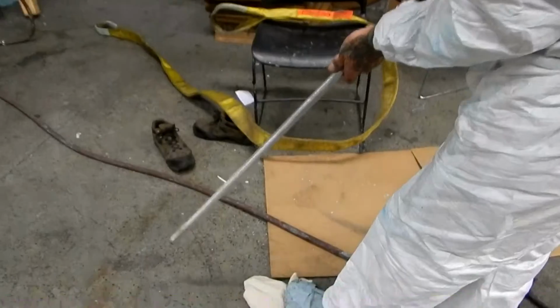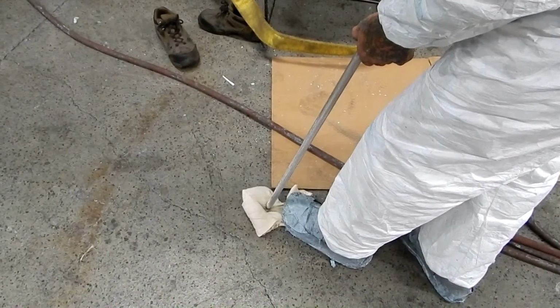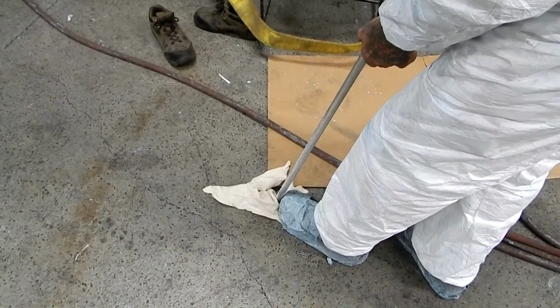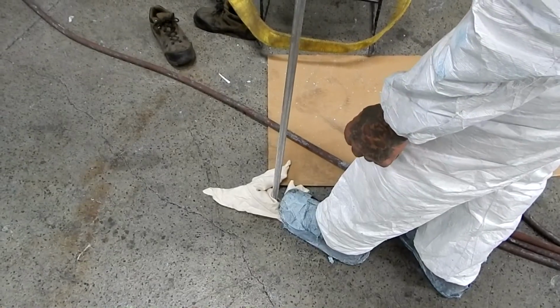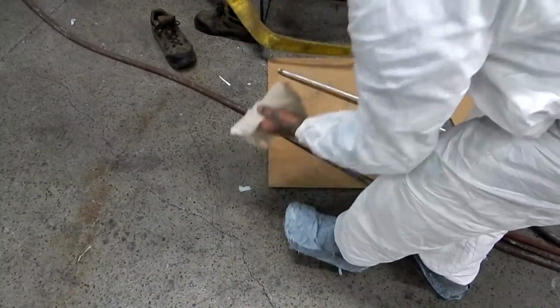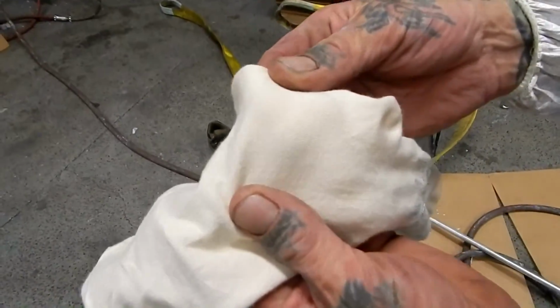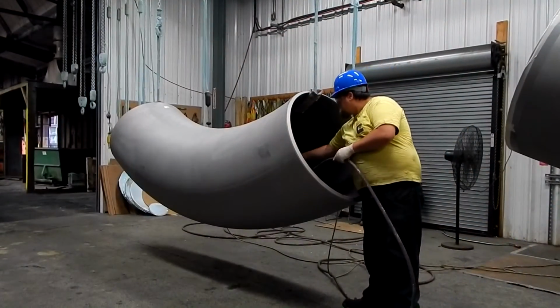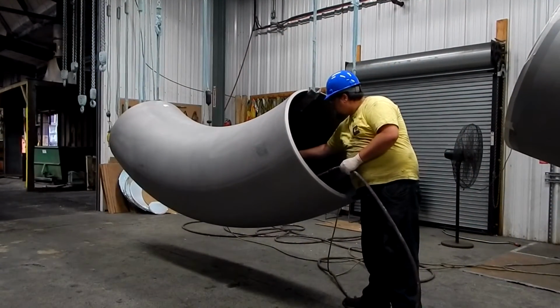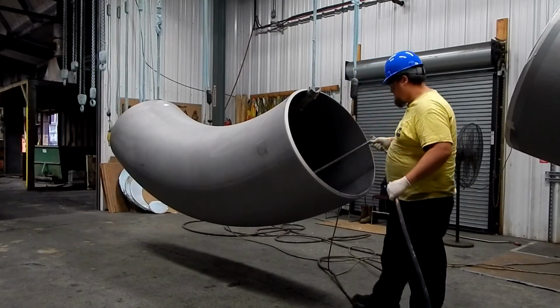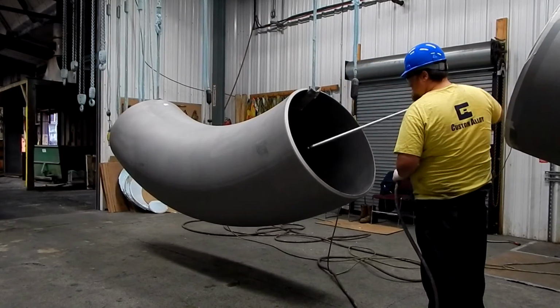Step 12. Compressed air quality blotter test. Spray the air from the air gun into a white rag to see if there is any moisture or oil in the airline. If there is, then this airline cannot be used to blow off the pieces. After you have checked the compressed air by doing the blotter test, you may use the air gun to blow the piece clean of any dirt, dust, or debris.